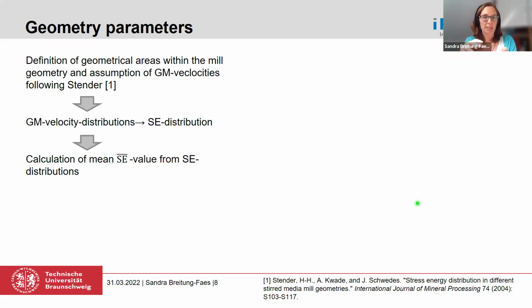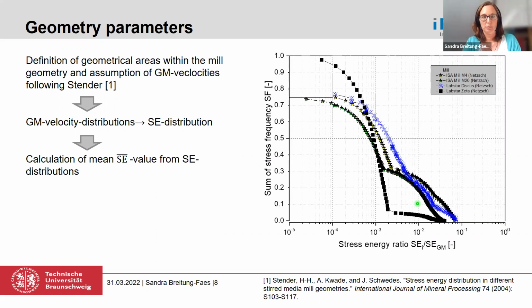So at least he took the assumption, for example, that at the disk, the grinding beads have the velocity of the disks, and the bigger the distance between the disk and the grinding medium, the velocity decreases with a certain gradient, which was based on fluid flow simulations. And therewith he was able to calculate at least grinding media velocity distributions. And with this, it is possible to calculate the stress energy distribution. And I did this for the 4 mills I showed you before, and you can see the result here. You can see here at least the calculated stress energy in relation to the maximum stress energy, which was the same for all the mills.